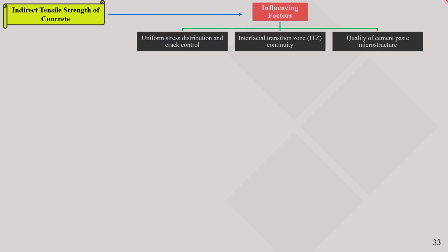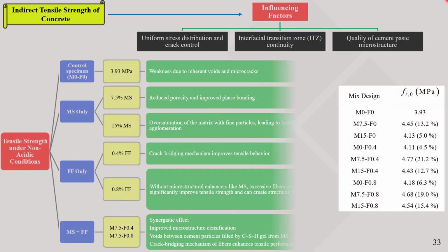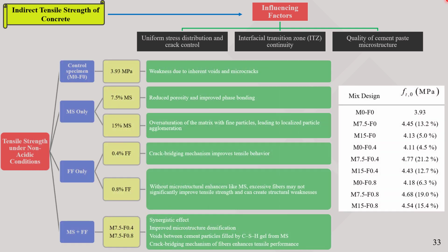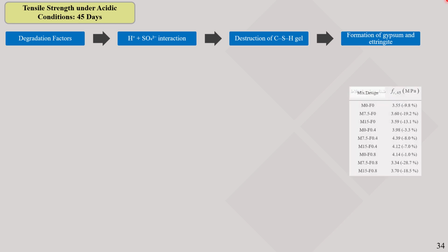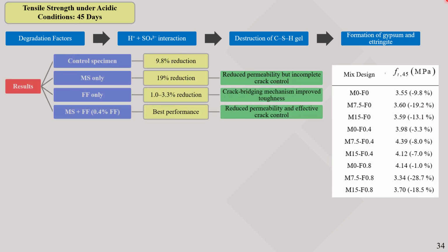For the indirect tensile strength test, 3 factors were influential: the quality of the cement paste microstructure, the bond in the transition zone and stress distribution, and crack control. Under non-acidic conditions, fibers had a positive effect, and the best performance was observed in the combined samples. Under the 45-day acidic condition, the same degradation mechanism occurred, and once again, the combined samples performed best, especially when